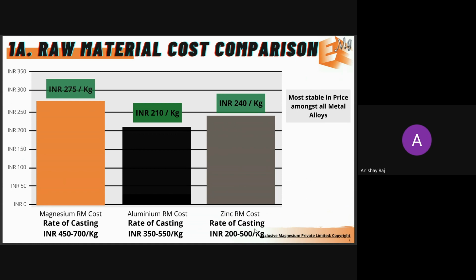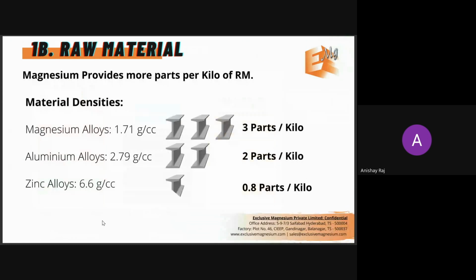Zinc I just mentioned because of die casting, but you can look at aluminium and magnesium specifically. So there's a huge overlap. That is one point. The second is that you have to remember, because of the lower density, if 1 kg of magnesium is giving you 3 components, aluminium can only give you 2 components, and even lesser in zinc, right? So there's saving in terms of raw material as well, the amount of raw material used.